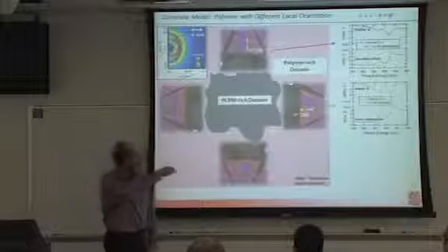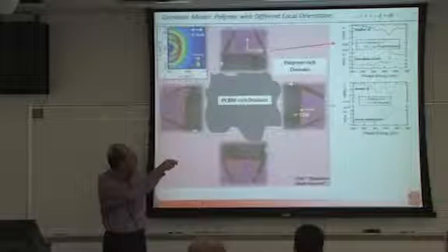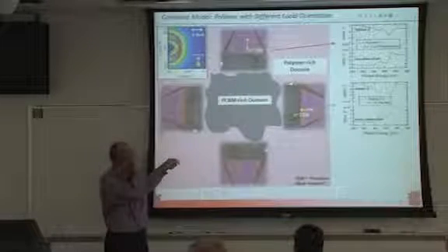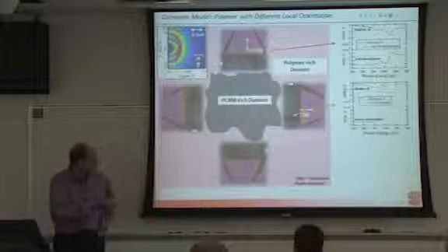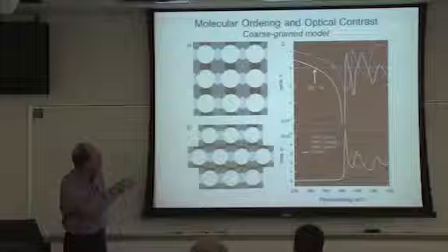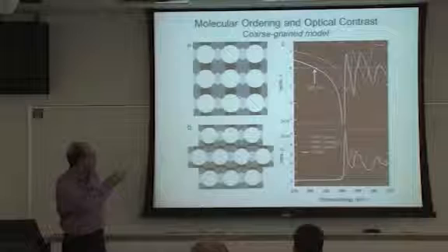So if I had a round PCBM domain with the polymer on the outside and the polymer would be face-on all the time, then my transition dipole moment would rotate. It would modify my optical constants. I would get high absorption here, which changes, low absorption here because the dipole moment is perpendicular, which gives me a high delta. Here I have more absorption, which gives me a lower delta, and the PCBM is fixed, and we can go through this and look at this more coarse-grained and make it rather square, make it round with 6 sectors.